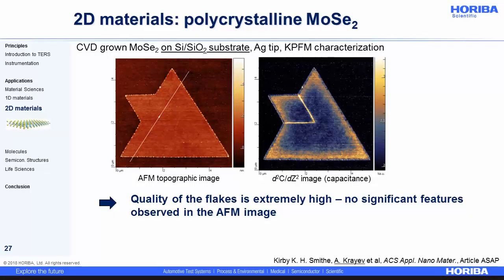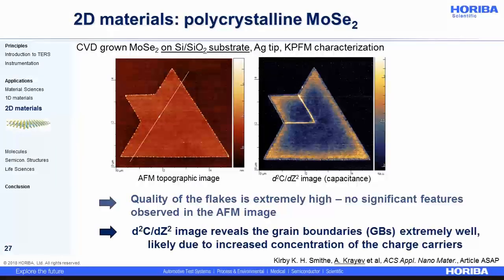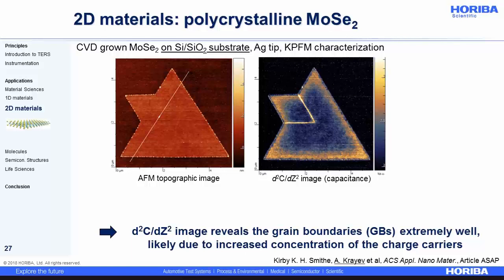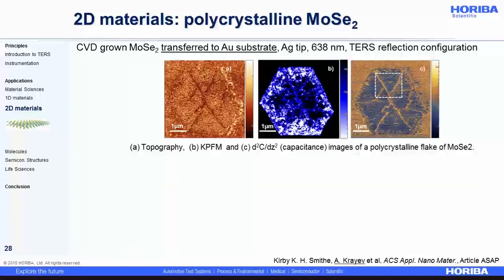But while probing the capacitance of this flake through the measurement of its second derivative, this is completely another story. We can see here now clearly the grain boundaries standing out extremely well. So let's study now the evolution of those grain boundaries after the transfer of this flake of molybdenum diselenide. Indeed, studying the transfer of 2D materials is crucial for the fabrication of heterostructures based on the stacking of 2D materials. And this also requires an optical characterization technique on the order of tens of nanometers.